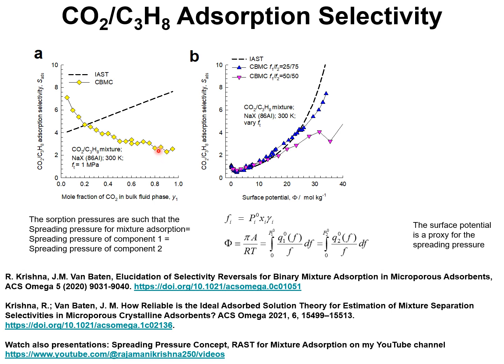So the composition dependence of the adsorption selectivity for mixtures in which the total fugacity is held constant, the trends are incorrectly estimated or predicted by the IAST because of congregation of CO2 around the extra framework cations.